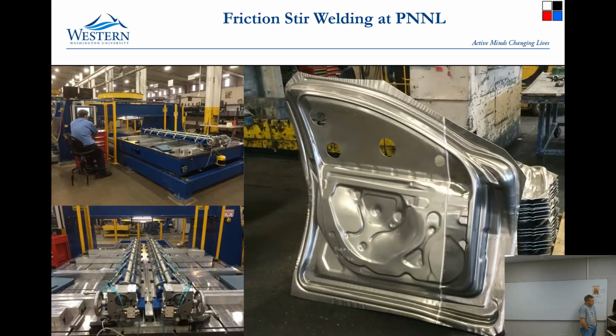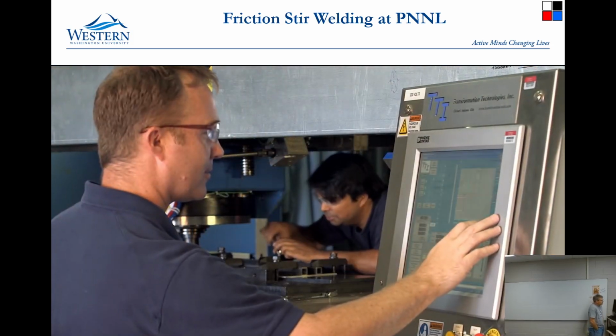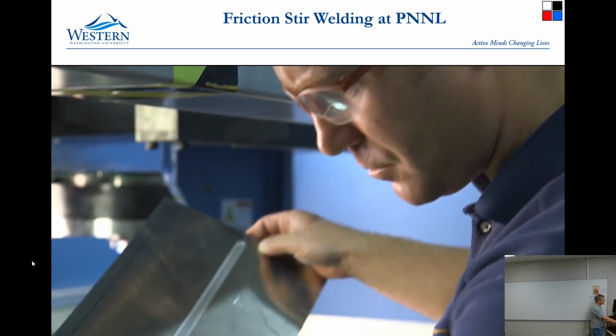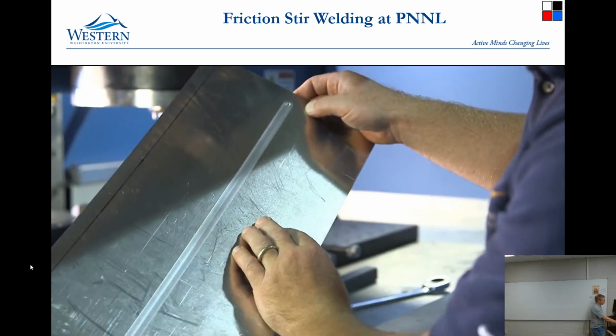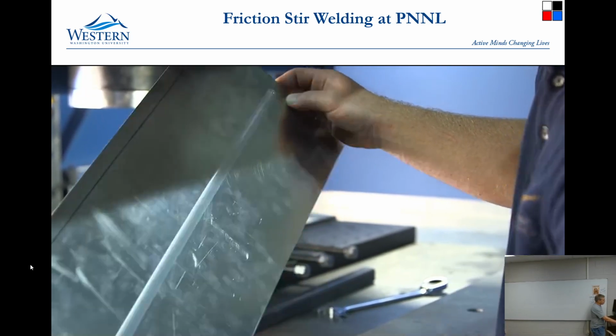By working directly with Taylor Welded Blank Company, they were able to put in their facilities in Monroe, Michigan, a dedicated friction stir welding machine that's capable of producing up to 250,000 blanks a year. This is a first for the automotive industry. One of the surprising things that we found was that as we increased the speed, the performance of the materials increased as well. Whether we're speaking of surface quality or formability, higher speed made a better joint. High-speed friction stir welding is enabling more widespread use of aluminum alloys throughout the automotive industry.